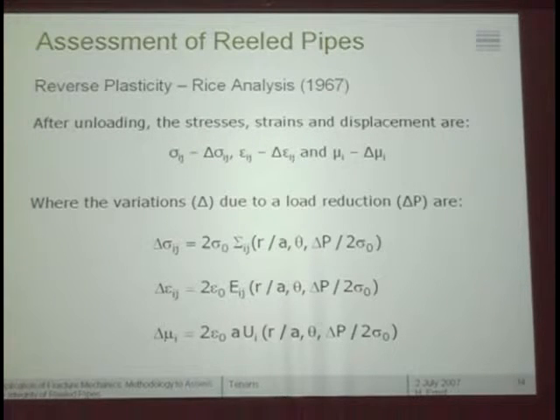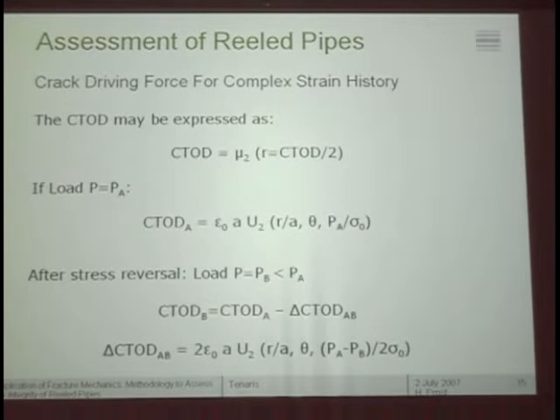he proposed that if we were to unload from some load A to a load B, we will see then that the sigmas will be decreased by the delta sigma, the epsilon by the delta epsilon, the mu displacement by that delta mu, in a way that the functional dependence will be the same as what we had before, except that you should replace the loads by delta loads everywhere, and also, if we are using this kinematic hardening, that simple rule of multiplying by 2 the mu will do. So with that, you are able to calculate what are the stresses, strains, and displacement after unloading. And of course, obviously, one particular displacement that we are interested in is the CTOD itself, that can be seen as a mu2, which is taken at R equals CTOD/2.